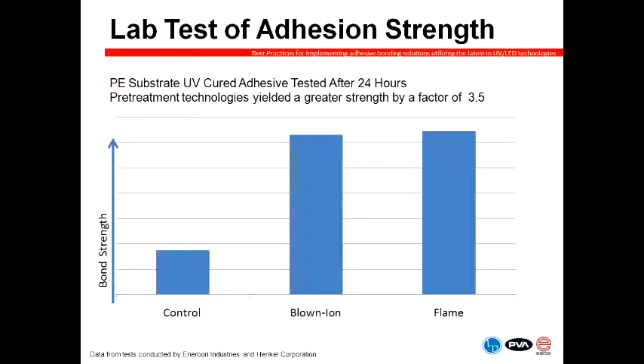So what we're seeing on this slide is a test that we had conducted with an adhesive company on a polyethylene substrate with UV cured adhesives. The far left bar shows the control sample, which was not treated, and the two on the right, one with blow and ion and one with flame, the strength of that bond was 3.5 times greater after plasma treatment. So the effect that you can have is pretty significant when you choose the right technology combined with the right adhesive and the right curing solution.